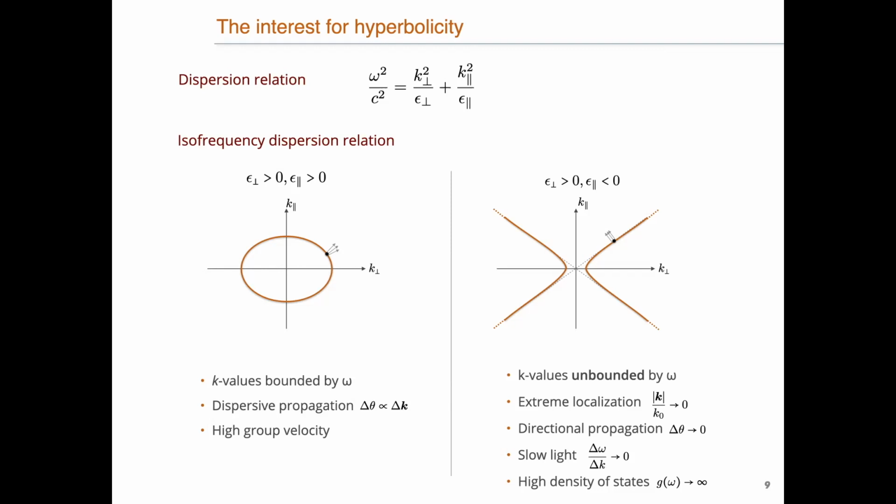Okay, so in gallium selenide, the wavelength in vacuum we're talking about is 40 micron. If you go to hBN, it's going to be, I think, if I remember well, about 15 micron. So basically, phonon polaritons have huge wavelengths. And whenever you put them inside the material, you can strongly confine them, okay? Play with this dispersion curve and achieve Ks that will be significantly smaller, for example submicron. What we have achieved is about 400 nanometers, a factor of 100.